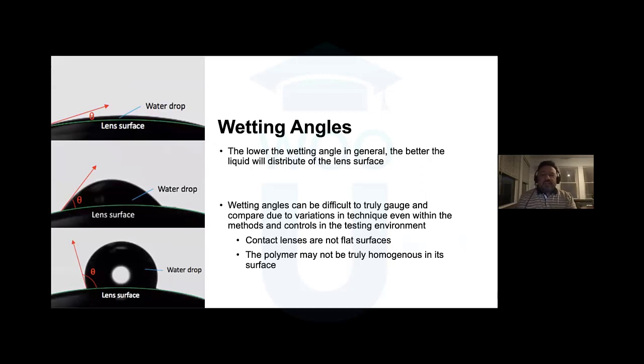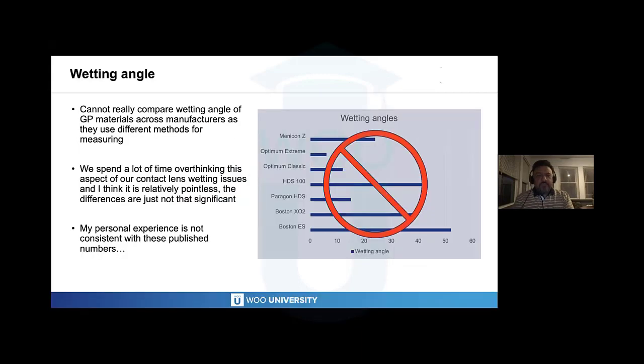And the reality is that the different manufacturers are going to use different ways of reporting their wetting angle. And so you may have a situation where one lab presents their wetting angle as 10 using the sessile drop method, and another lab reports their wetting angle as 30 using the captive bubble method. Well, what is that? That's apples to oranges. You can't really compare them side by side. And so most of the time, the wetting angles that are reported are really kind of difficult to understand and difficult to interpret, particularly when you're going across manufacturers.